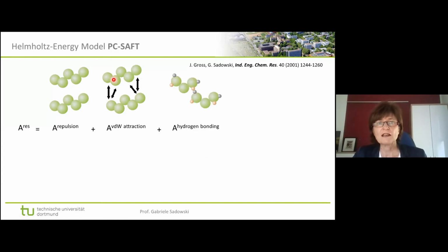The third one, which is the A in PC-SAFT and also in SAFT, is the one that accounts for hydrogen bonds. And of course, as we are dealing with water, as for example the absorbed component, we have a huge amount of hydrogen bonds. And also most of the pharmaceuticals, the APIs, are indeed hydrogen bond formers. So this is the only chance to get at least a little bit of them in water, because usually these are huge molecules. So we do need this contribution, and then we have a fourth one for accounting for the fact that molecules may have a dipole or a quadrupole, and we even have a fifth one, which I do not show here, in case the molecules also carry charges, which is not the case for the examples I show you here.